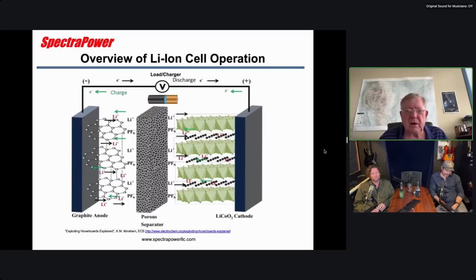But if you want longer life, charge it slowly so that it allows time for the lithium to move in, intercalate into the graphite, and don't charge it to 100%, or especially don't discharge the cell to 0%. In both cases, you're stressing the electrodes, and so it will reduce your life. Also, don't do the full rate. In other words, when you operate at a real high rate, it tends to stress the material more. And so, anyway, the point is, if you want the longest life, charge it and discharge it slowly, and only go 0 to 20 to 80%.